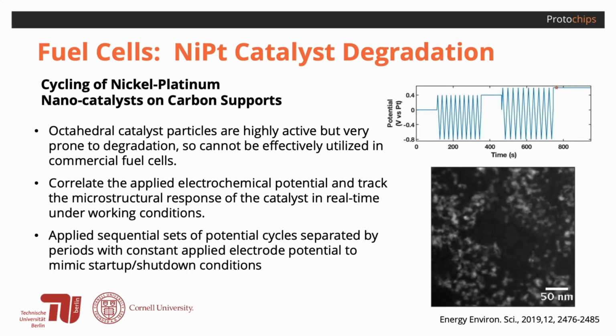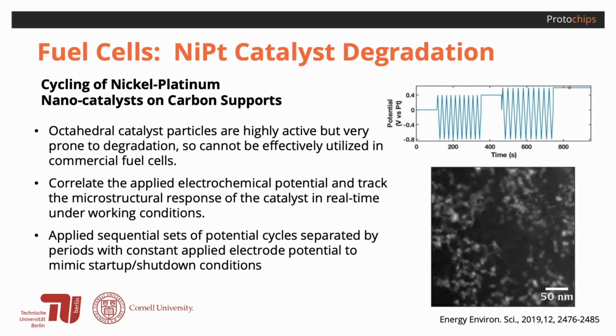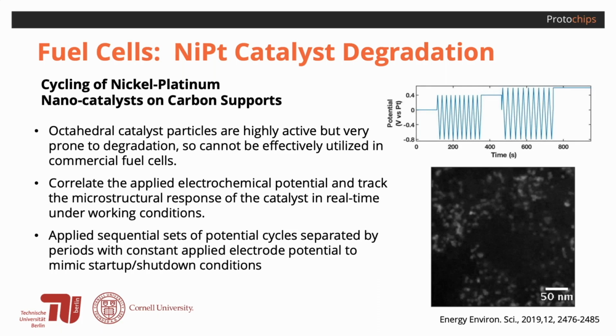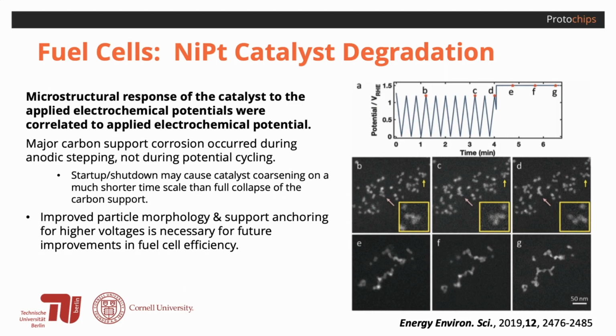However, when we reach the final high voltage hold, we can see that significant mobility along the carbon support is occurring. During those potential cycles between 0 and 1.2 volts, both particle coalescence and particle motion was observed in the TEM images. In these examples, the red arrows are indicating individual snapshots taken during that portion of the potential sequence.